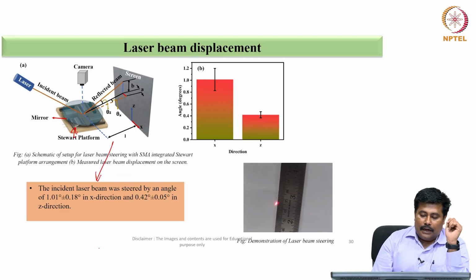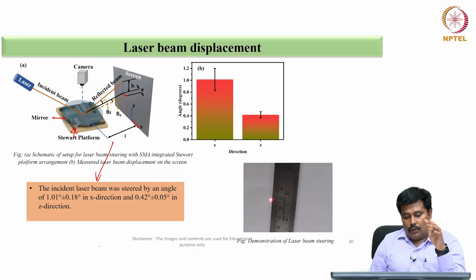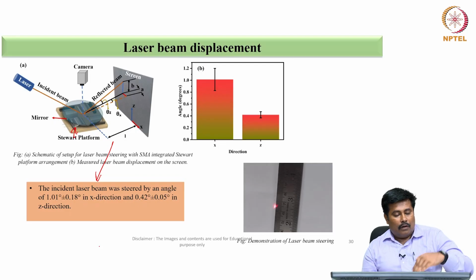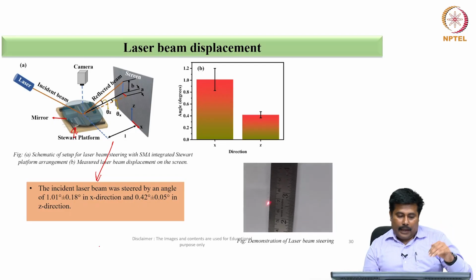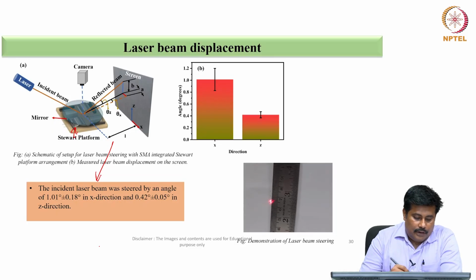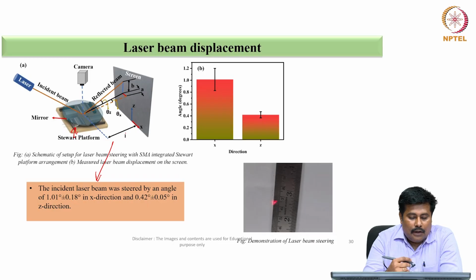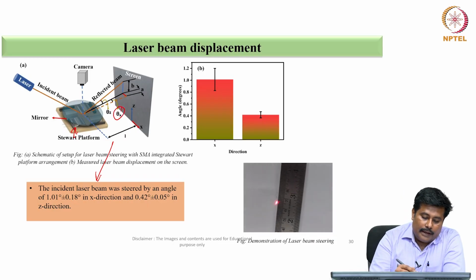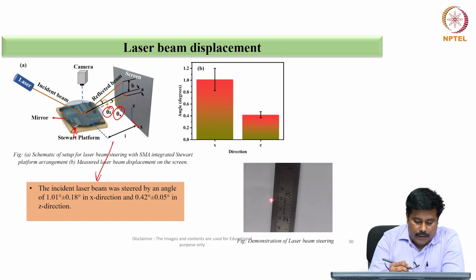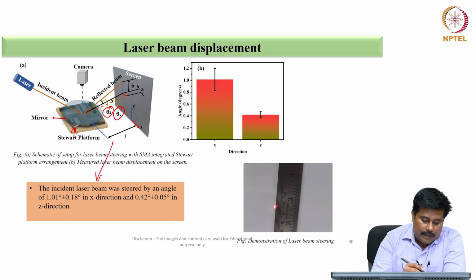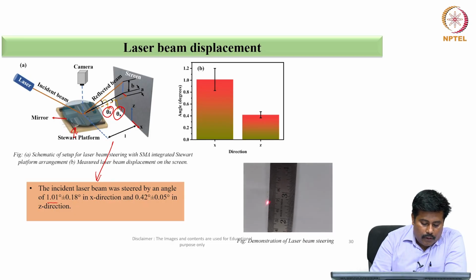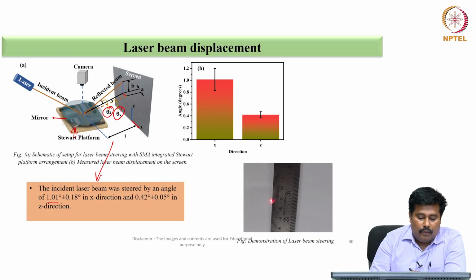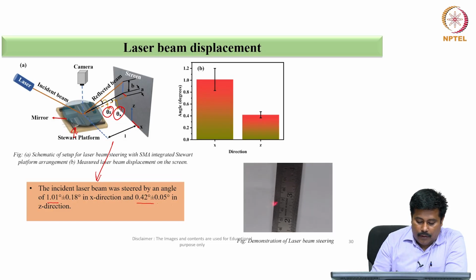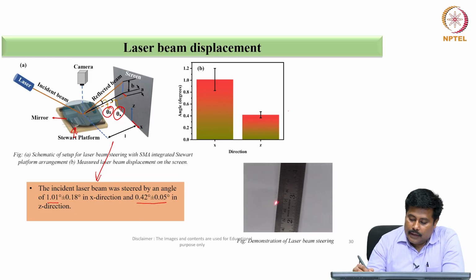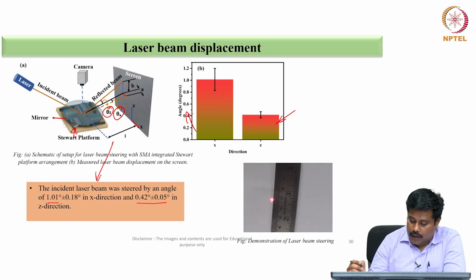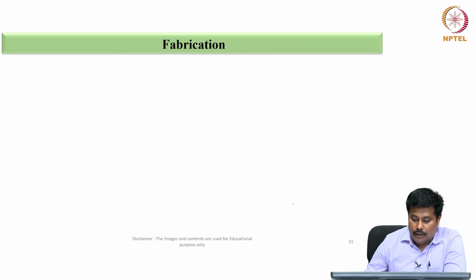Okay, and this is the incident laser beam, and a camera is used to capture the overall orientation of this particular beam and its appropriate characteristics. In that aspect, if we see, the orientation has different types. One is along the theta x orientation, and the other one is along the theta z orientation. As far as theta x orientation is concerned, around 1.01 degrees plus or minus 0.18 degrees could be achieved, and with reference to the z direction, 0.42 with 0.05 could be achieved. So the direction has a direct relevance towards the degree, and appropriately a laser beam is being diverted over here.